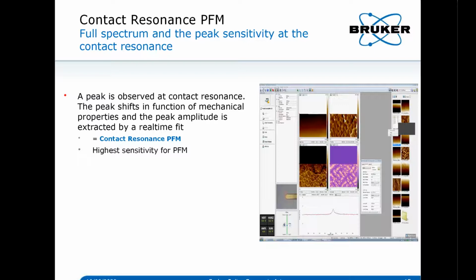The contact modulus can be quite different, and this different contact modulus will change your resonance frequency at this specific location. So in the DataCube mode I mentioned earlier, we can sweep the frequency. By doing this, we can always make sure that we are collecting the piezo response at the strongest point, which is the contact resonance frequency at this specific pixel. In this way, we guarantee that you always get the strongest PFM signal for the whole image.